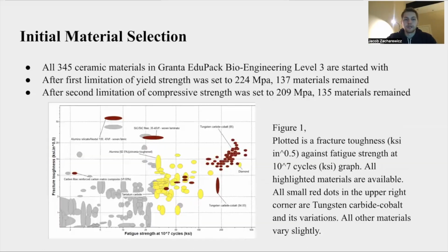So for my initial material selection, I started off with 345 ceramic materials that were offered in level 3 of Granta EduPack. And after I set my first limit of yield strength of 224 megapascals, only 137 materials remained. And after my second limit of compressive strength of 209 megapascals, 135 materials remained. And this figure here is the first fracture toughness versus fatigue strength graph I was able to graph. And as you can see, there is a wide range of materials.